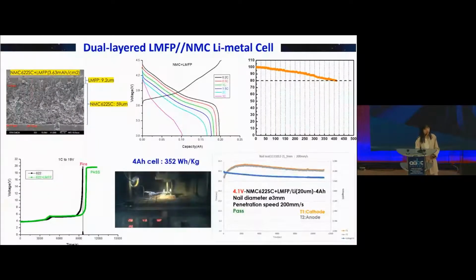So we also have the 4 amp-hour dual layer lithium metal cell with LMFP in the top layer. The cell achieved an energy density of 352 watt-hour per kilogram and retained about 80% of capacity after 400 cycles. The cell charged to 4.1 volts passed the safety test and also the overcharge test up to 19 volts. So this is the content for our LMFP material and also the cell. I'll move on to the next part.